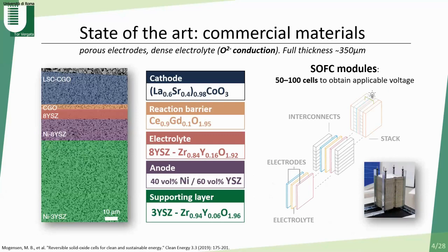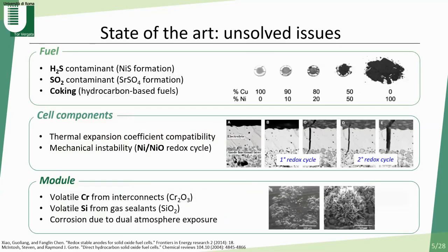Here is a scanning electron micrograph cross-section of an anode-supported flat cell. As you can see from the bottom, there are different colors. There is the supporting layer, the micrometric anode, which is a composite made of 40% nickel and 60% YSZ, yttrium-stabilized zirconia, the very thin electrolyte, and a reaction barrier made of gadolinium-doped ceria between the electrolyte and the cathode material, which is a perovskite oxide. This is a conventional cell, but the state of the art of materials for SOFCs still presents some unsolved issues.